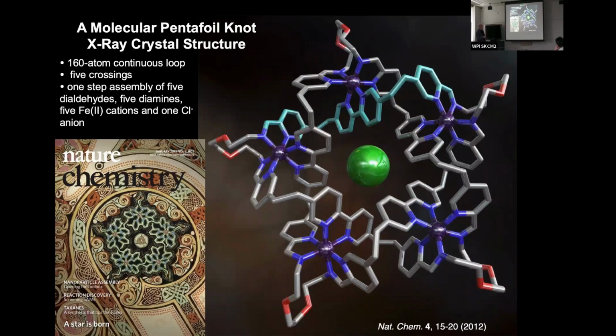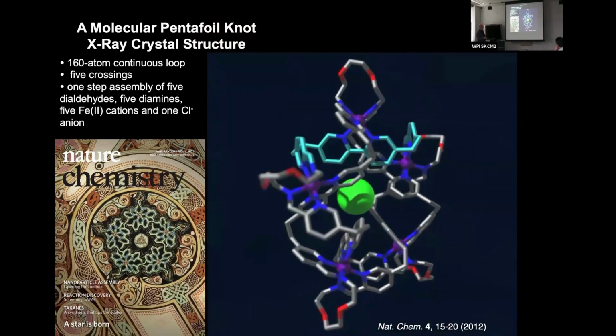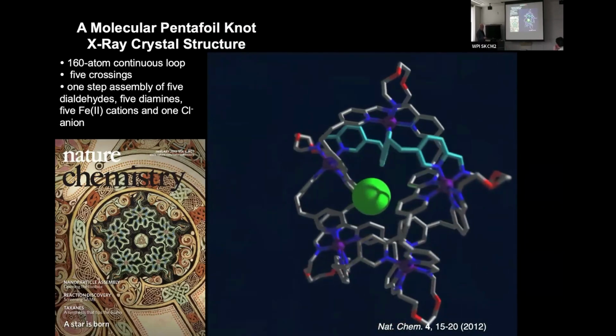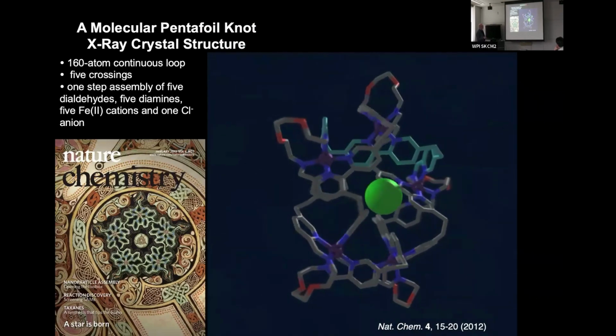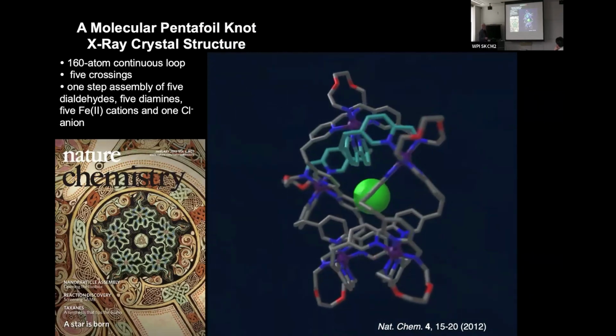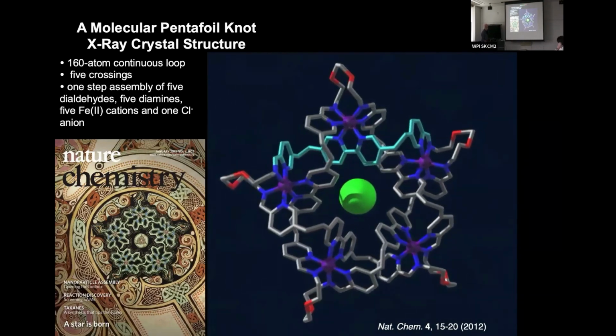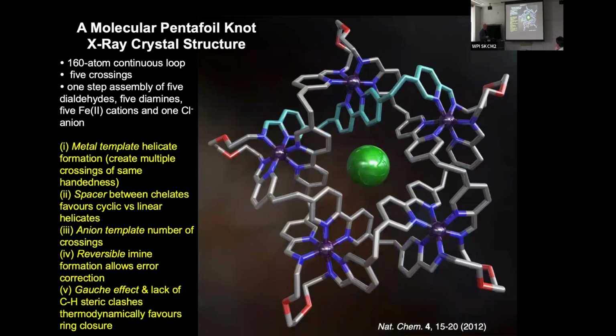It's got 160 atoms in that continuous loop, and it's made in one step from this self-assembly reaction of 5 of those dialdehydes, 5 of those diamines, 5 of these iron cations, and 1 chloride ion held in the middle that templates its assembly. And if we rotate the crystal structure, you can see this lovely double helix that's formed from the ligand around the metal ions. And even though this is a simple assembly process, it sort of belies the complexity that's involved in the design that leads to the assembly of the knot.